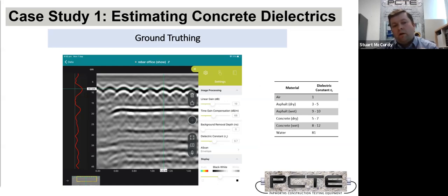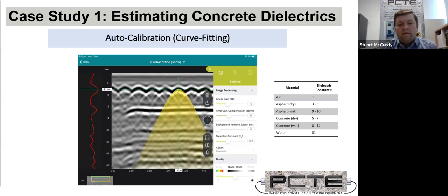So on ground truthing, now that I know my dielectric's 9.7, I use that for the rest of my scan, and I can click on any point. In this case, I've gone back to the top layer reinforcement, and now it's told me that it's 81 mil. Okay. That's a much better estimate than just guessing what the dielectric was. This is the autocal. So I bring up this yellow curve. I fit the curvature of that yellow one to the actual hyperbola, and then it gives me a pretty good estimate for what that dielectric was. And I don't need to do a core.